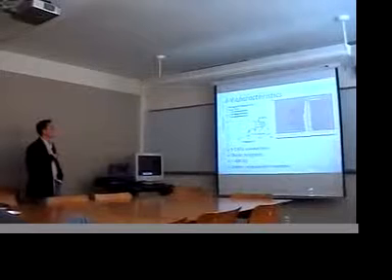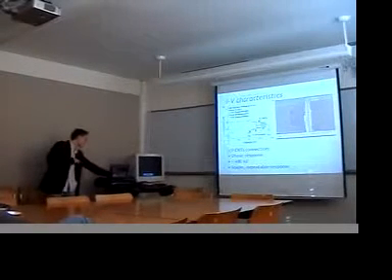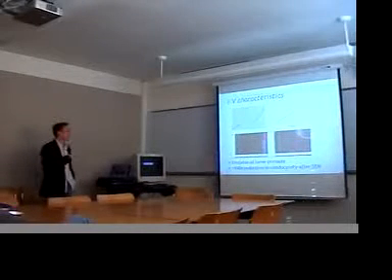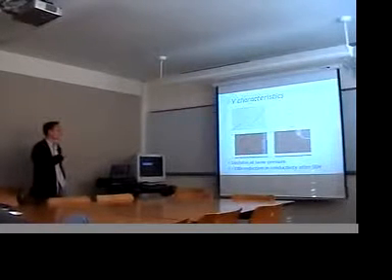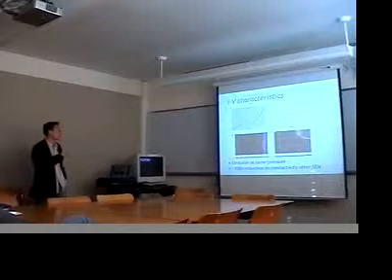So this is one of the IV curves that we got. Over here we have 9 successful carbon nanotube connections. As you can see, it's very ohmic and it's a repeatable response, and we get around 480 kilo ohms total. Unfortunately, our devices are not always that stable. So this is what I mean by the interface coupling. You can see that this is done under the same condition, but every time we do the same thing, it just gives all sorts of very unstable IV characteristics.